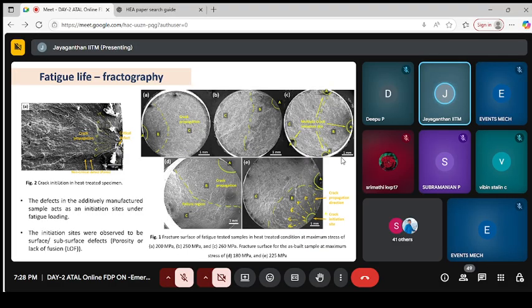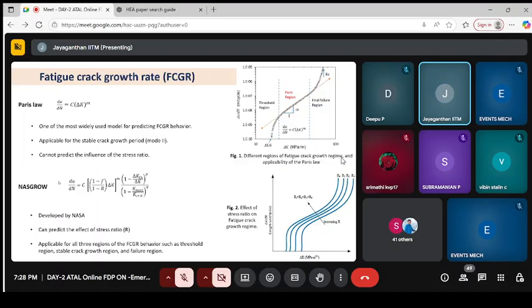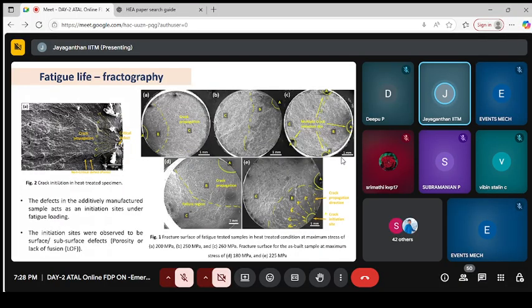And again, for the fatigue tested sample, through fractography, if internal cracks are present, we looked at how they tend to move under cyclic loading. That also we did, a thorough characterization of the fatigue tested sample. And we have seen that the fatigue properties of the heat treated sample are much better. And again, the previous analysis just assumes you are applying the load under dynamic conditions. Load could be tension, compression, or a combination of both.